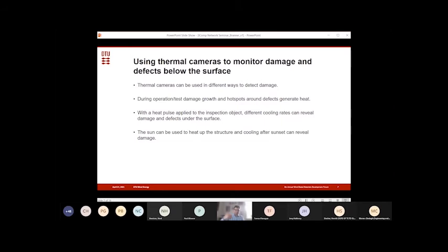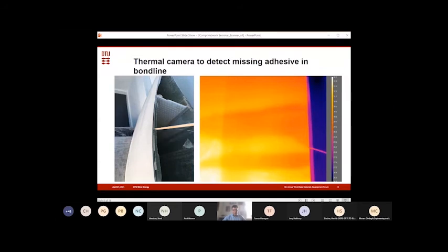A heat source can be the sun, so this is definitely possible to use, and many drone companies use this to inspect blades at sunset. So when the sun goes down, then they can detect the damages by looking at the difference in radiation. So this is an example of a blade structure with poor adhesive bonds, where it has been exposed to heat, and then the thermal camera will show clearly that there are some areas where the bonding is good, and some areas where it's bad. So thermal cameras can be used for that.